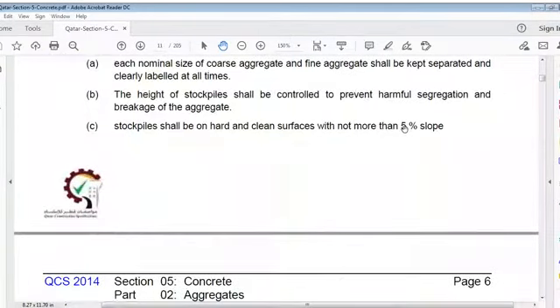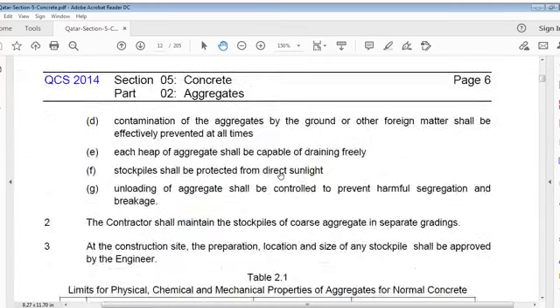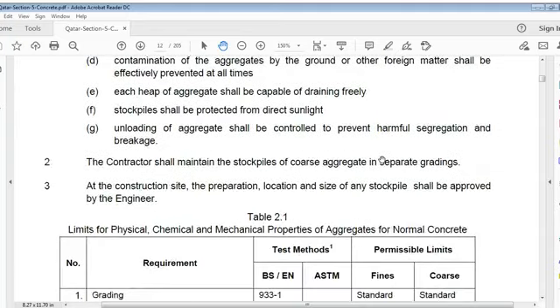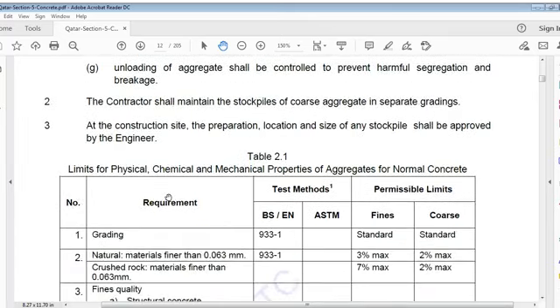5% slope, mind it, it's not 45, it's 5% slope for stockpiles. Hard and clean surfaces with not more than 5% slope, for the purpose of drainage, etc. Contamination of aggregates by ground or other foreign matter shall be effectively prevented at all times. Each heap of aggregate shall be capable of draining freely. Stockpiles shall be protected from direct sunlight or shaded. Unloading of aggregate shall be controlled to prevent harmful segregation and breakage. Contractor shall maintain stockpiles of coarse aggregate in separate gradings.